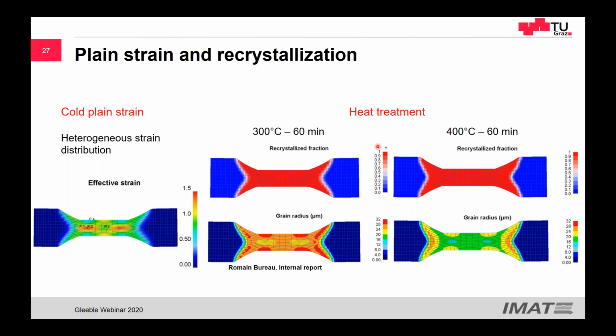Yeah, okay, so we have the strain distribution here. This was cold deformation, so here we don't have a temperature distribution. What we have is a strain distribution due to friction. It took a very long time to see which friction factors we should use here. We are not experts in friction coefficients, so we adjusted the friction factors just to get the same shape of strain that we got with the hardness map. So we know that if we increase the friction factors more, we will have different shapes. We may have only one cross or two crosses or no cross at all if we have homogeneous deformation.